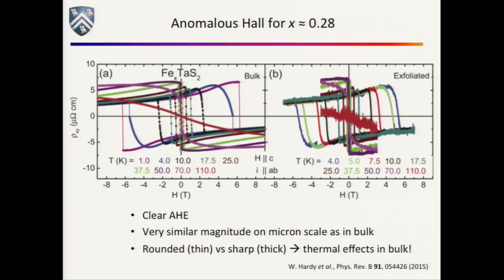The reason these transitions are so sharp in the bulk, we now think, is that it's actually a thermal effect. Once you really start coercing the spins, you end up dumping a bunch of thermal energy into the lattice, and we think the thing kind of runs away and immediately flips. Whereas in the thin crystal, we think that the heat can get out pretty effectively, so you don't see this sudden thermal avalanching.